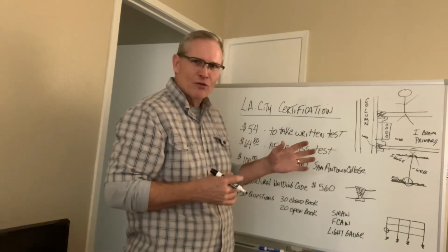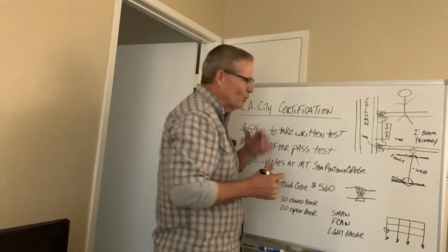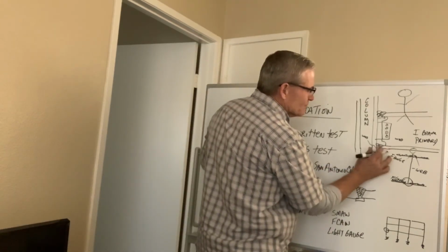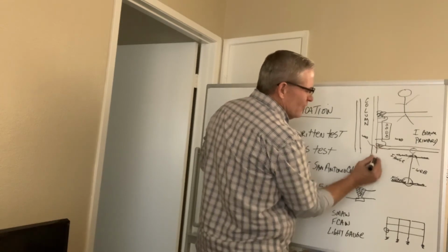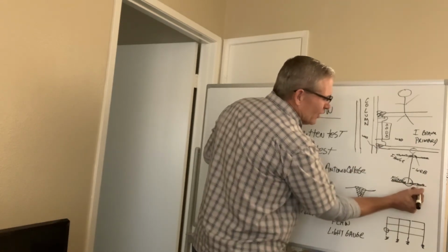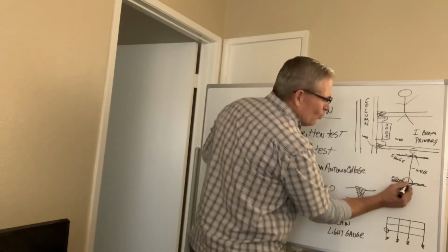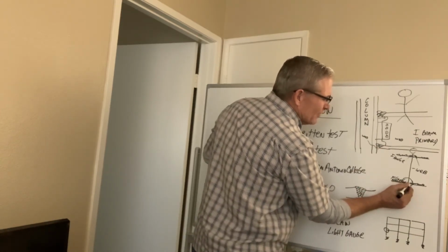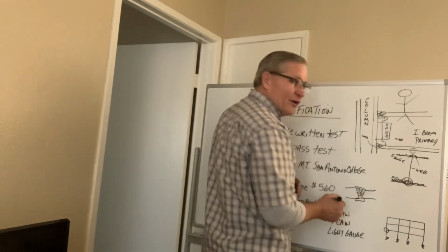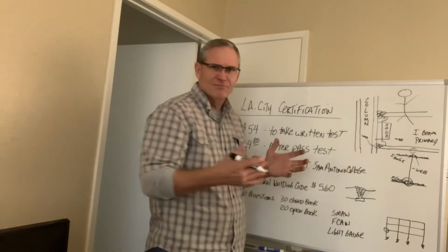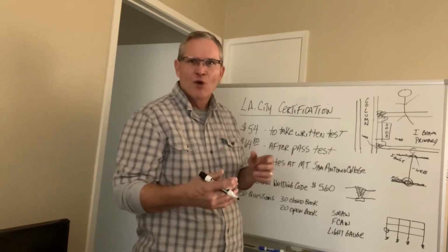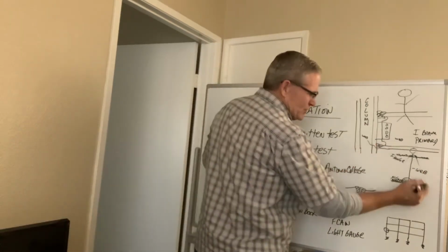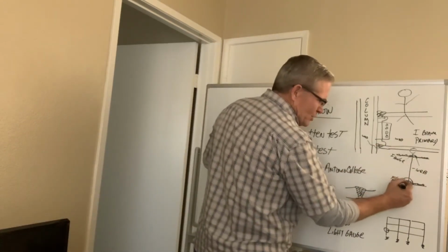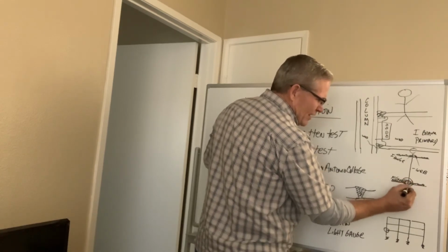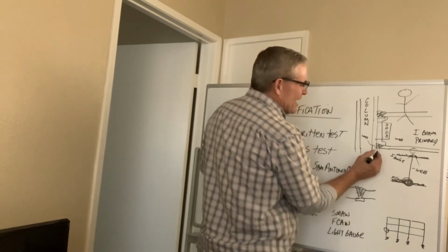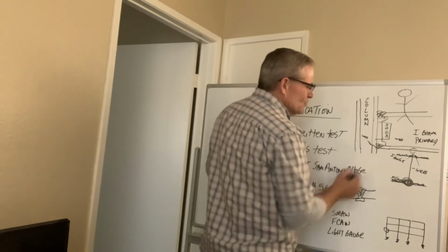And after the Northridge earthquake, that's when that was stopped. In other words, they have to remove this backup strip, backup plate on this lower flange, and they had to air arc this weld to make sure that where this web interfaces, there was no buildup of slag in that area. So in essence, it caused the welders to be much more concerned when they're doing the welding. As opposed to just reaching over, doing a quick weld here, and then reaching over and doing a quick weld here without much cleaning, they ended up with slag entrapment right here, and that's what was causing this crack to go into the column itself.